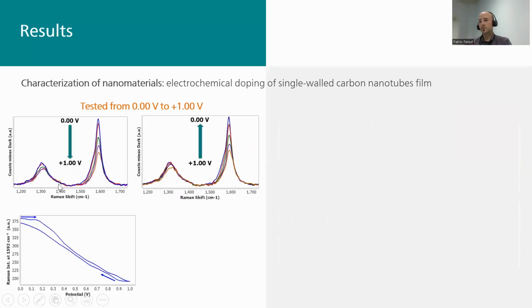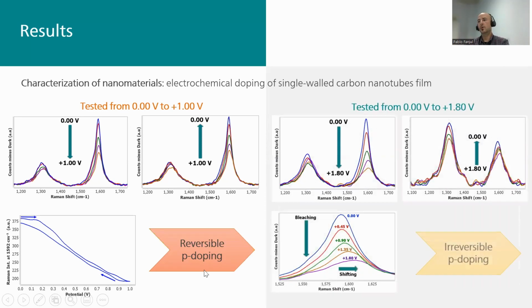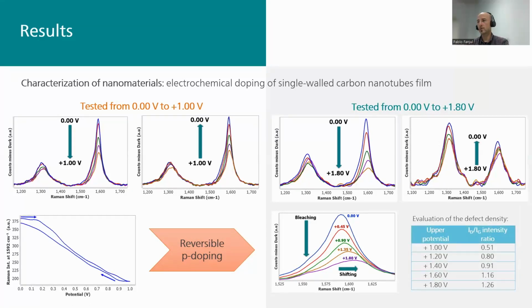That's more or less what I show here in this slide. So initially going from 0 to +1 volt, we have a reversible p-doping. However, when we move up to 1.8 volts, the doping is irreversible. So we are generating too many defects in the structure, and we are not able to recover the initial configuration of the material. In fact, if we follow this ratio, that is usually the one that is measured, the ratio between the intensities of the D and the G band, it is going up very quickly with increasing potential, and it cannot be recovered during the backward scan.